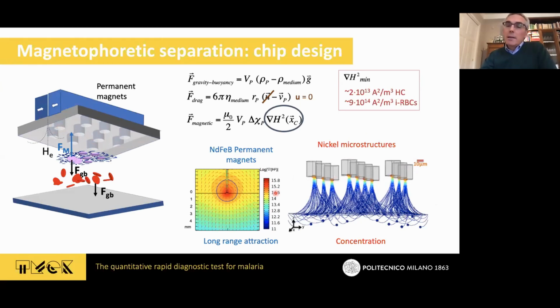But in order to magnetize the nickel post, we have to use an assembly of permanent magnets. We are using neodymium iron boron permanent magnets in this configuration in which we have 2 north poles facing each other. In this way, you have a very, very strong gradient produced here. If you calculate the gradient of H² which is needed to find a magnetic force capable of counteracting the gravity and buoyancy force, you immediately discover that you need a very strong gradient of H², in the order of 2 × 10¹³ A²/m³ for a hemozoin crystal, and 9 × 10¹⁴ A²/m³ for infected red blood cells. So not negligible fields are needed. But okay, with this configuration, we solve the problem.